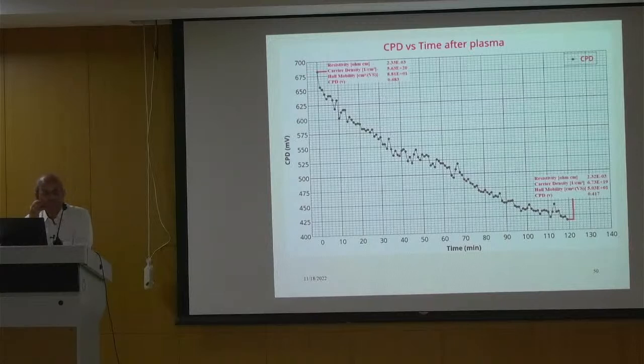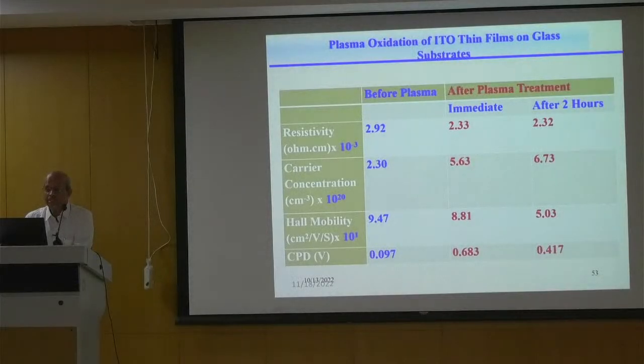So what is the point we have to take here? If there is a surface modification you would like to attempt, there are relaxation effects. Until and unless you make the surface completely relaxed, you may not be able to do any further processing to make a device. Otherwise the device is going to fail. So a dynamic observation of what is happening on the surface is a very important result with the Kelvin probe technique. There is no other technique which will do that. So these numbers are very important.